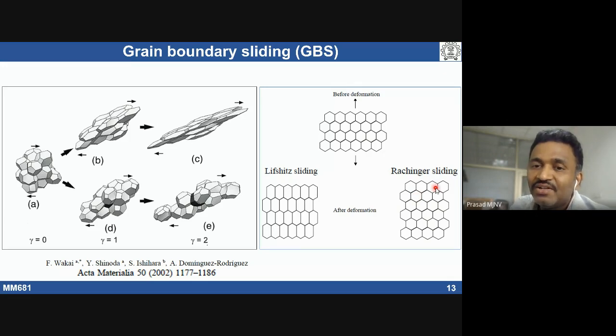So both the things can happen in materials, but it depends on what type of mechanism is accommodating the grain boundary sliding. Grain boundary sliding is happening in both the cases, but the type of accommodation mechanism is going to be different in both the cases.